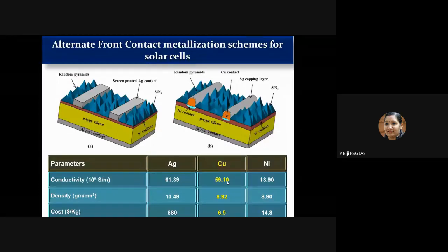Diffused copper at the junction increases the leakage current. It can also act as a deep level impurity and form traps, which can reduce the carrier lifetime. So what you need is not to directly deposit copper on the surface of the solar cell. You need a seed layer, which is nickel. Nickel as a seed layer will increase the adhesion as well as the conductivity. While sintering, it will form nickel silicide at the interface of the silicon and the nickel. That will improve the adhesion as well as the conductivity of the metal lines. In that way, you can block the diffusion of copper into the silicon, the emitter surface.